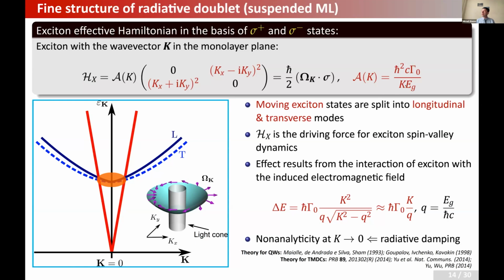It's the band gap of the material, or more precisely, the exciton emission energy. And there is also the exciton momentum in the denominator. If you look at this formula, it turns out that it is kind of non-analytic for small exciton momentum. This is because the states of excitons with small wave vector, smaller than the wave vector of the photon, are within the radiative cone. And that is why these states decay radiatively.